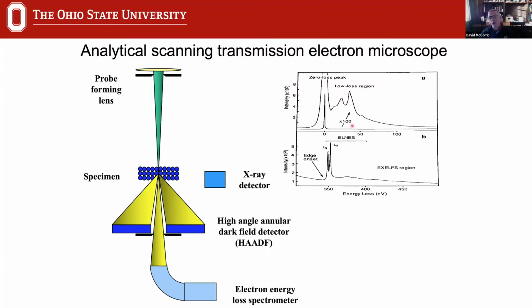And then as we go up in energy loss, in the region up to maybe about 40 or 50 electron volts energy loss, we see excitations between the valence and the conduction band, including collective excitations such as plasmons. And as we go further out in energy, we're on a decreasing background, we'll then see superimposed ionization edges that are associated with inner shell excitations, where we excite electrons from a deeper lying core level in the solid into the conduction band. And we can use these to not only identify the type of atom present, but we can actually learn about how the atom is coordinated to the other atoms around it in the solid.